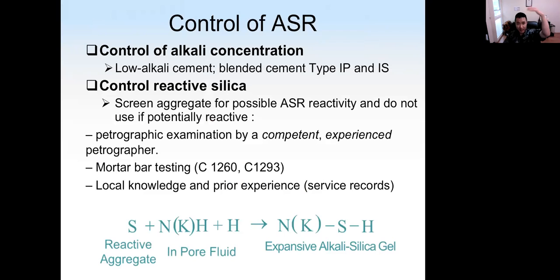Okay, so we talked about the mechanism for ASR. Then let's look at how we can control ASR. Because ASR is caused by reactive aggregate with alkali from the pore solution together with moisture, one way to control ASR is to control the alkali concentration from the cement. So we can use, for example, low alkali cement, or we can use blended cement. Blended cement is Portland cement together with slag or fly ash, which will also reduce the alkali content in cement. We can also control reactive silica.